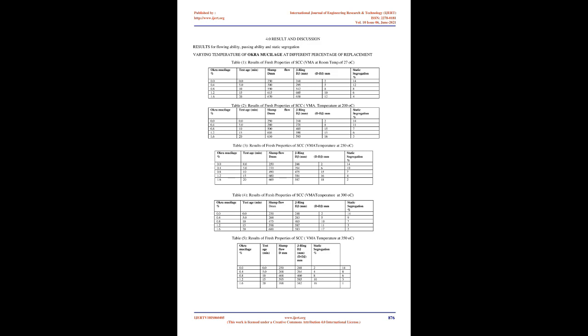Cubes of dimensions 150 mm by 150 mm by 150 mm were cast. All samples were allowed to cure in curing tanks filled with fresh water. The curing process was done for 7, 14, and 28 days. After curing, cube samples were tested in a compressive test machine. The strength tests were carried out carefully on the best attained samples from the stock of cast samples for different percentage